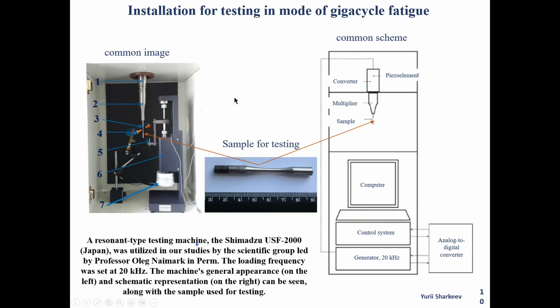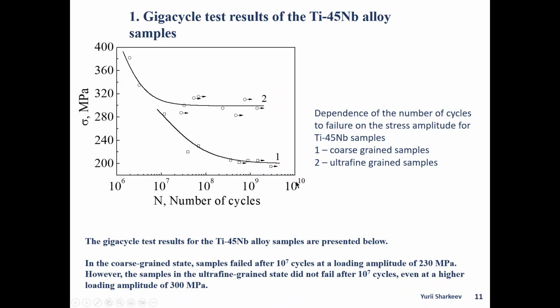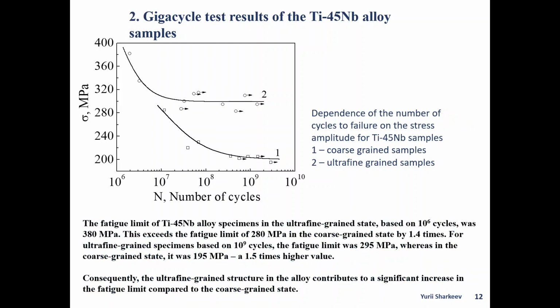The machine's general appearance on the left and schematic representation on the right can be seen, along with the sample used for testing. The gigacycle test results for the titanium niobium alloy sample are presented below. In the coarse grain state, the samples failed after 10 to the power 7 cycles at a loading amplitude of 230 megapascals is presented. However, the samples in the ultrafine grain state did not fail after 10 to the power 7 cycles, even at a higher loading amplitude of 300 megapascals.